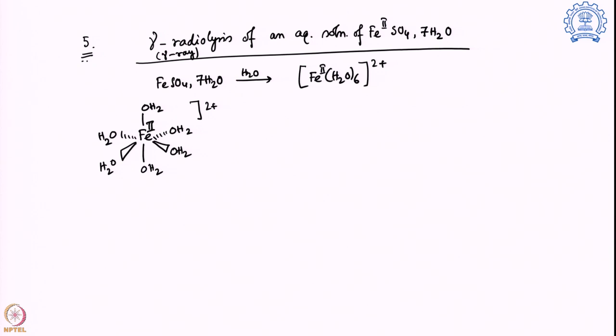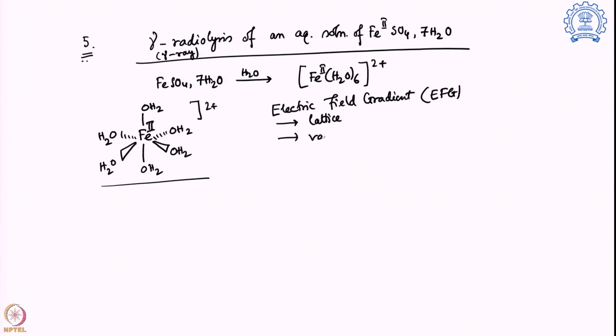Now before going further, let us first look at how the Mössbauer spectra of this particular system will look. We have covered that in an earlier segment, but just to recapitulate: iron plus 2 system in octahedral geometry, how should it look? In terms of electric field gradient, or EFG, it depends on two factors. One is the lattice, that means the coordination geometry, and one is the valence or distribution of the electrons. In this molecule, you can see that it is bound in a very symmetric octahedral geometry. So you do not expect any lattice electric field gradient because there is no asymmetry over there. However, the valence electric field gradient I do expect to see.